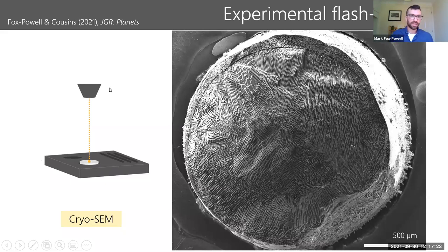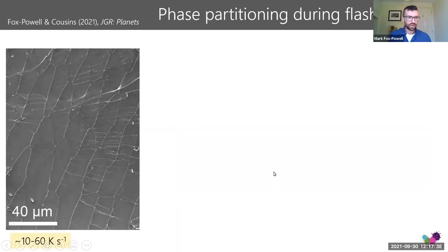This technique is really fantastic because it allows us to see the actual physical partitioning going on within the droplet. And as you can see, there is structure here in the interior of the droplet. So here's a closer look at that structure. What we're seeing is effectively a brine vein network. Even at these really rapid cooling rates of 10 to the 1 to 10 to the 2 Kelvin per second, we're getting this templating of a brine vein network as solutes are effectively excluded from crystallizing ice.